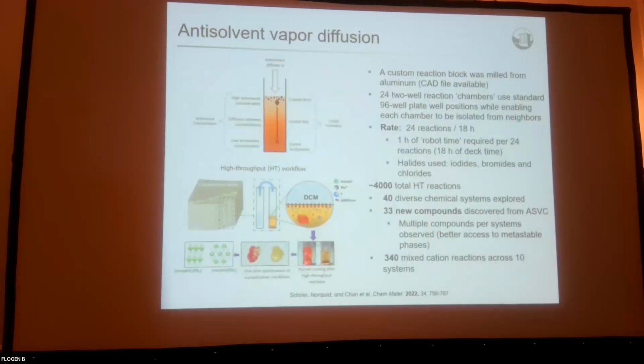And so the next route that we took was anti-solvent vapor diffusion, where we have a mother liquor with all of our solutes, and an anti-solvent, typically dichloromethane. Dichloromethane, by vapor pressure, diffuses into the mother liquor and changes the solvent properties, gradually inducing crystallization. We get a concentration gradient of the anti-solvent across the vial.